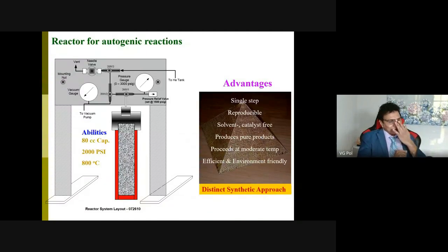Now this reactor, especially developed for this reaction, has multiple advantages. Namely, it is a single-step reaction. You don't need any solvent. It is a dry reaction. You just need solid plastic waste and it becomes carbon. It makes a pure form of carbon. You don't need acid or base or water to clean it up later. And the temperature is not too high. The reaction is carried out at lower temperature because when the hydrogen is released, it creates a pressure. You can hold the pressure together, eventually making sure that everything is in a greener shape.